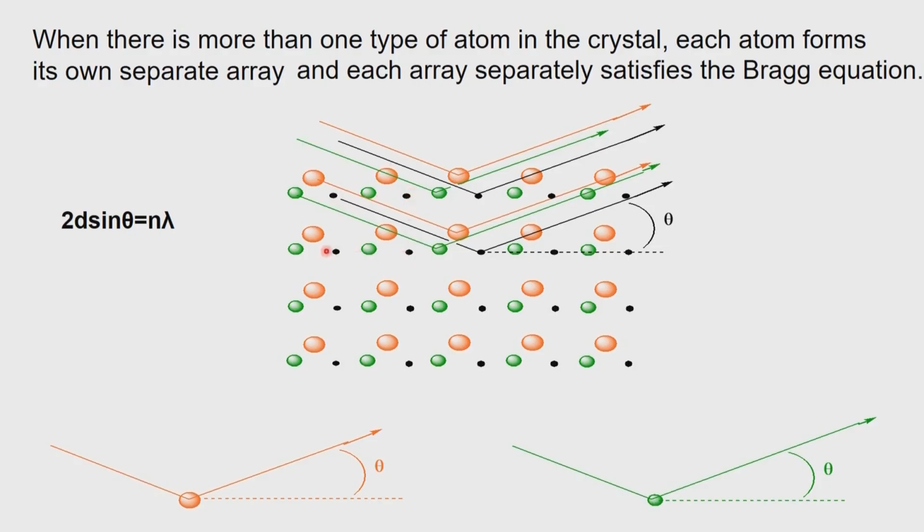So, if this is the lattice that is defined, and we are in the direct space, then when X-rays are shone, each and every atom will follow Bragg's law. Let us say there are 20 atoms associated with this one lattice point, each of them will follow Bragg's law. So, the red atom will also scatter at theta, the blue atom will also scatter at theta, but what you measure is the reflection which is coming from the plane. Now, each and every plane is a point represented in this two dimensional diagram, and therefore this particular point is a plane which satisfies Bragg's condition or Laue's conditions.